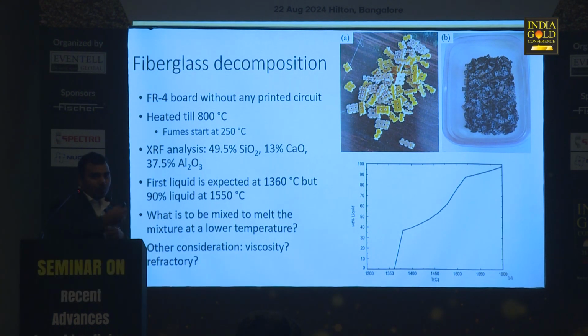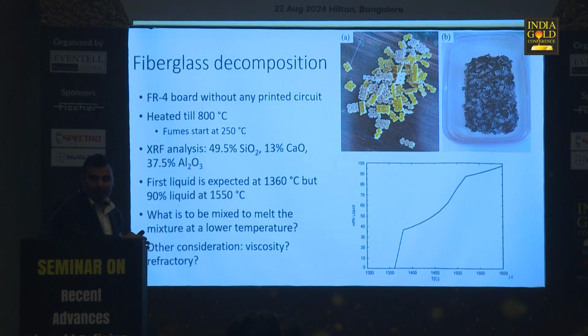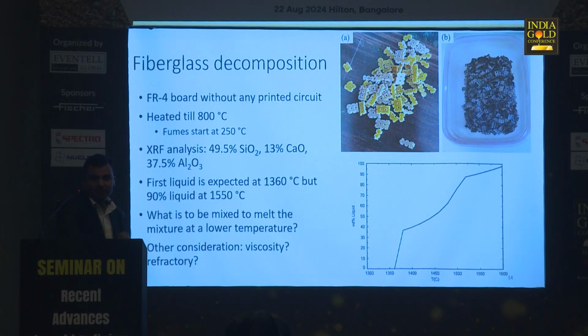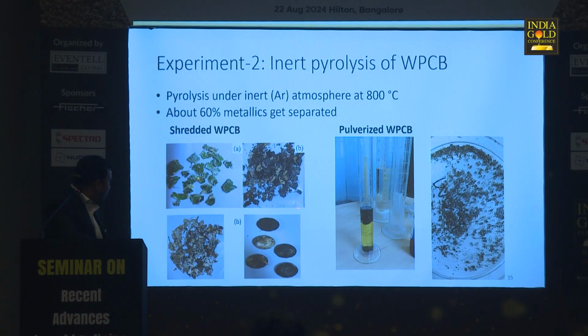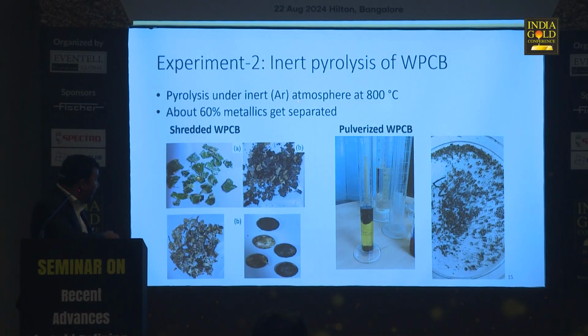Of course, one can go and do trial and error and keep mixing boric acid, calcium oxide, etc., and see what happens. But we use the FactSage to do the calculation, design the flux, what we are going to make, and we did a mass balance. And as you will see, we did not even need a second trial. In the first trial, you will see that we are able to melt it. Before that, I'll come back to that.